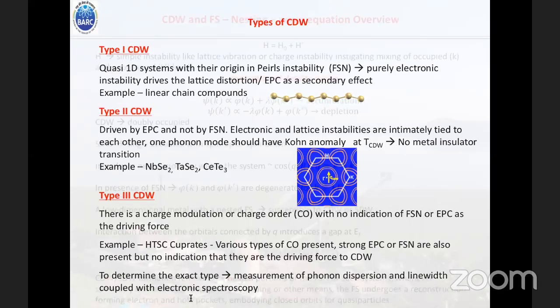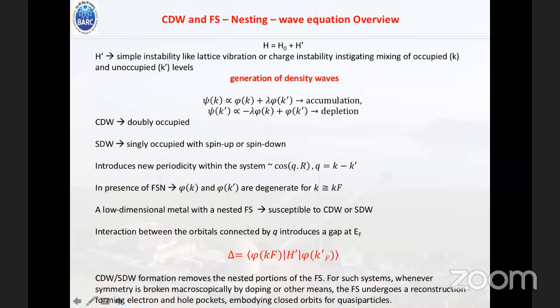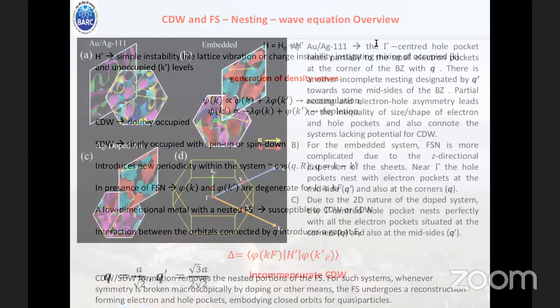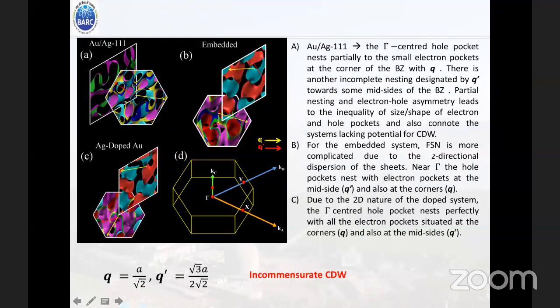So what we have done here is calculate the AuAg(111) surface, for an embedded and doped Ag-Au system. We have calculated the Fermi surfaces, and shown that for AuAg(111) there are hole pockets at the center, and two kinds of nesting vector, one towards the mid side of the hexagon, another towards the corner of the hexagon. Whenever we look at the Fermi surface here, those are partial nesting. There are very small electron pockets here, so this is not a potential candidate for Fermi surface nesting. Rather, the embedded and doped systems have more complete nesting.